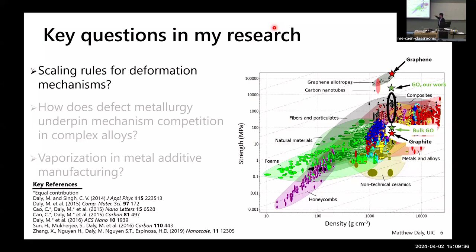All of a sudden, you get this order of magnitude decrease in the mechanical properties. And this is a log scale. So you're going from hundreds of GPa, or 100 GPa, all the way down to 100 megapascals. This is significant. And really what this has to fundamentally do is a shift from breaking in-plane bonds to interplane shearing mechanisms. But where we got interested, based on previous work we had done in the lab and work done by others, is looking at graphene oxide.